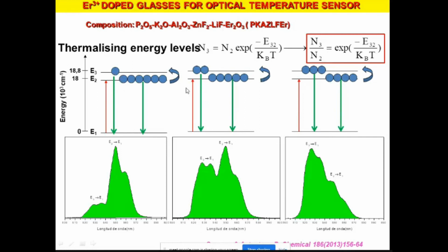If we keep on increasing the temperature, this thermally populated level gets population, and if we still increase the temperature, this level gets more populated. For example, you see, at room temperature, this level is less intense and this level is relatively more intense. And now at an average temperature, both levels are equal. When the temperature is more, the level which is low intensity at room temperature shoots up its intensity at higher temperature. So this material can be used as a sensor to measure the temperature. Rare earth doped glasses or glass ceramics or nano glasses are going to be used in optical sensors also.